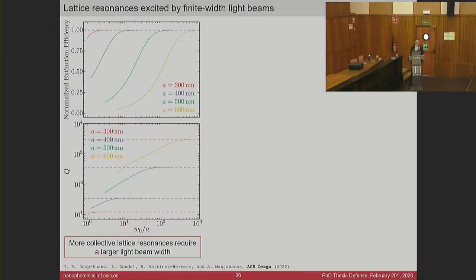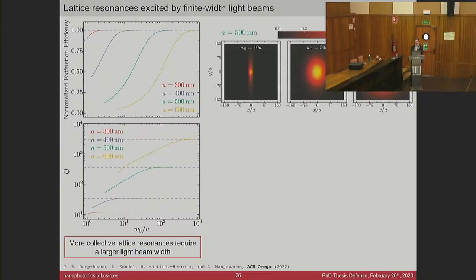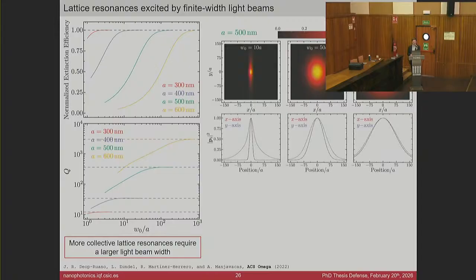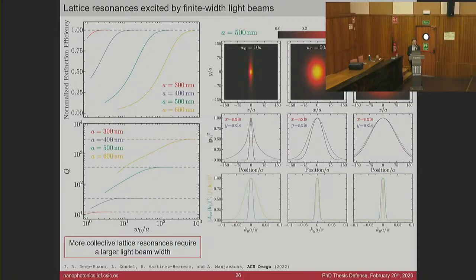This characterizes the far field properties of our modes, but it is also really interesting to analyze the local excitation of the dipoles. And we can see that there are huge variations as well, depending on the beam width. If we come with a beam that is really focused, we can actually observe how the excitation propagates. And since we are coming with x polarization, the interaction is propagating in the y direction. As we increase the size of the beam, then we converge to a limit in which the excitations of the dipoles follow more or less the profile of the beam. This is something that we can also observe by making cuts, but I'm not going to focus on this too much. And we also explore this by a reciprocal space study.